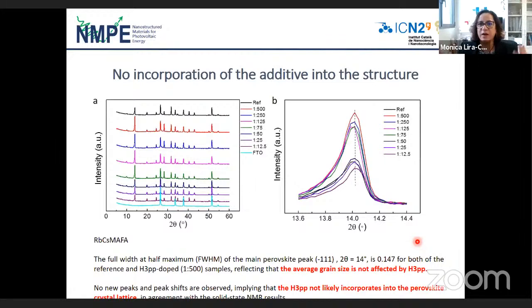So we try to analyze the material, and we realize that this additive is not getting incorporated into the crystalline structure, as shown by this X-ray diffraction analysis.